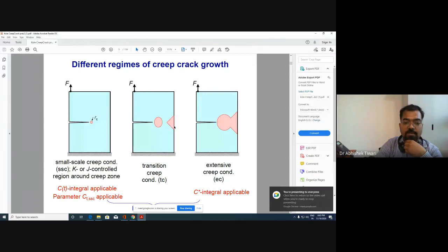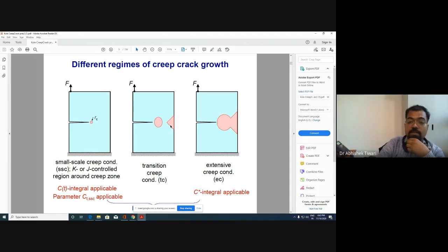That is, you have a backside plastic deformation. It can be a plastic deformation if you're talking about elastic plastic material. It can also be creep deformation, but in compression. Because backside is getting compressed. And compression will not cause a crack to propagate from the backside. Usually, it takes a lot of time for the compression to create a crack.